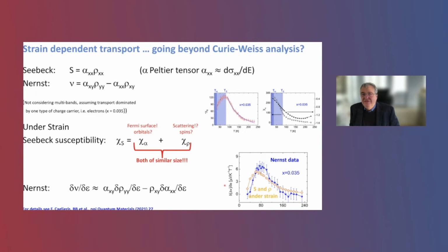So, strain-dependent transport: can we go beyond Curie-Weiss analysis? I will not go into details here on all these concentration dependences, but just mention that in principle we can learn a little bit more, and it's straightforward to do that. The Seebeck effect can be written as a product of a so-called Peltier tensor times resistivity. And this Peltier tensor is the energy derivative of the conductivity. This energy derivative means that you're very sensitive to details of the Fermi surface, of the density of states at the Fermi surface. What's well known is that if you have a peak in the density of states at the Fermi surface, the Seebeck effect becomes very large. And a similar formula can be written for the Nernst effect.